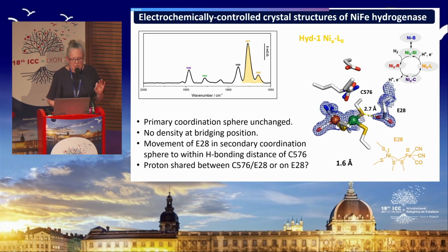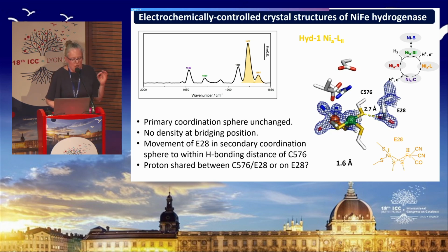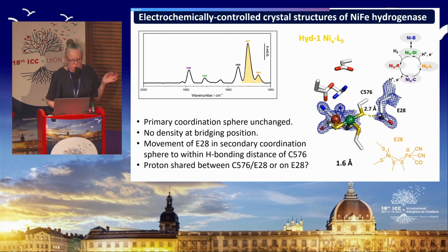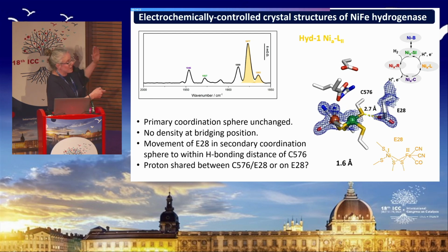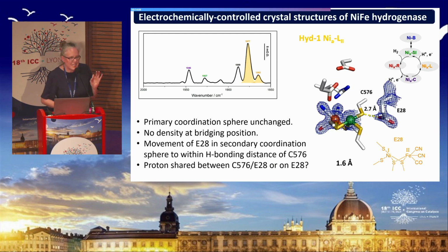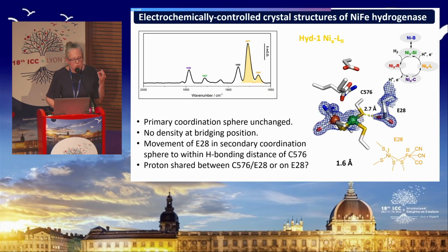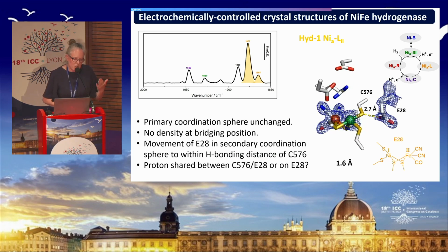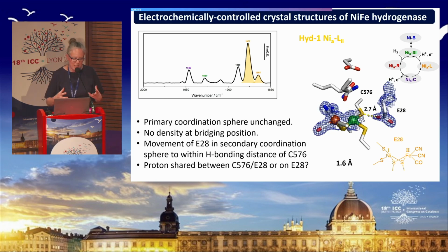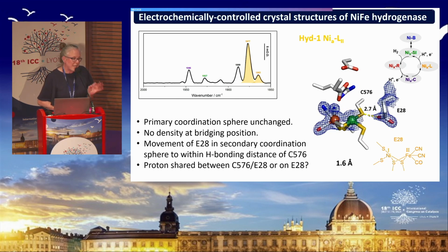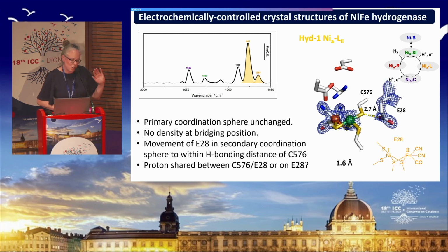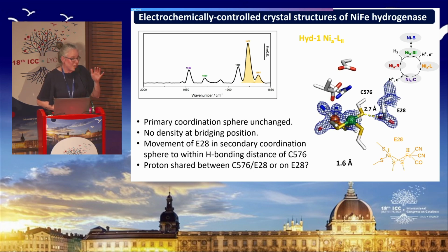The distance in the other structures is all around 3 angstroms or just over 3 angstroms. And here we bring it just close enough, at 2.7 angstroms, to be within the distance that people like Judith Klinman have modeled or measured from studies of mobility within proteins as critical to allow proton tunneling without needing major structural change in a protein.